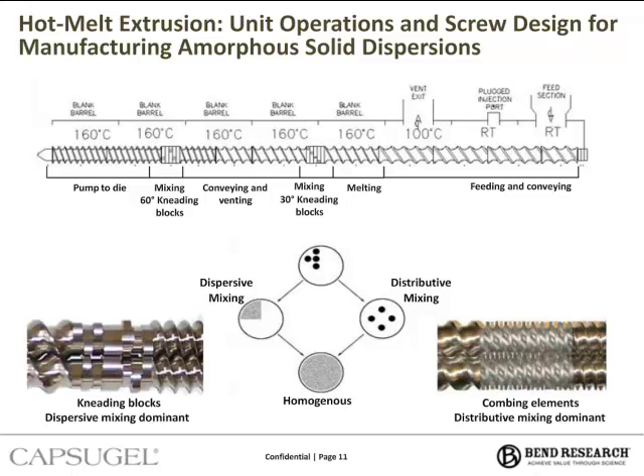Now the amount of mixing depends on if we're dissolving the API versus melting the API into the polymer matrix. And the 2 types of mixing, as seen on the slide, are dispersive mixing and distributive mixing. So dispersive mixing is the more intense mixing, and this takes place, we use something called kneading blocks to do this. Now the larger the angle, the more dispersive mixing. So a 90-degree kneading block is all dispersive mixing, and there's very little conveying, whereas a 30-degree kneading block, there's more conveying and less dispersive mixing.